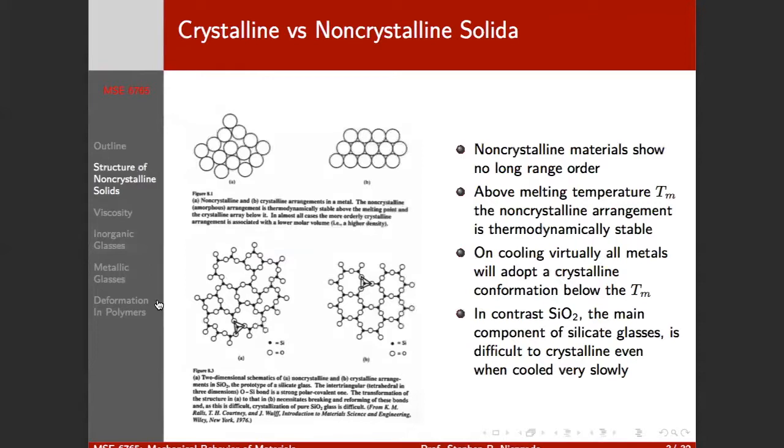That's the bonding that they want to make at equilibrium. They're stuck in a metastable state, but it's not like perfect rows. It's more of like a vacancy type structure where atoms are shifted a little bit from their positions. So they're not as packed as they should be, but they still have the right number of neighbors for the most part.